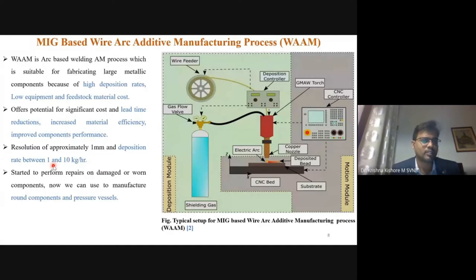The main advantages of this WAAM process are higher deposition rates and low material cost. That is, the powder cost is very, very high compared to the wire. So manufacturing of the wire is quite cheaper, and the feedstock material cost is reduced drastically. We will see a case study where we compare Inconel wire with Inconel powder. If it is 9,000 per kg for powder, here we are getting it at 1,200 to 1,300 per kg. So there is quite a good reduction in the feedstock material cost as well.